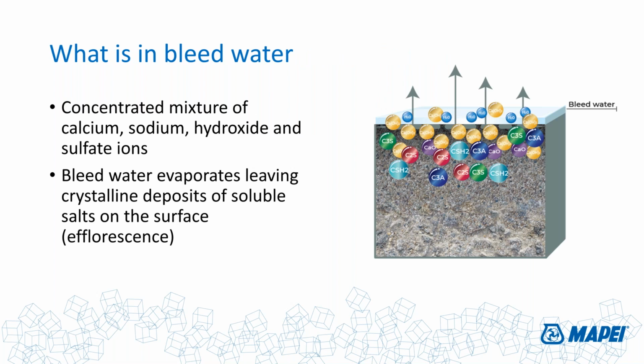That is again a concentrated mixture of calcium and sodium and hydroxide and sulfate ions that sit on the surface. And as that bleed water evaporates, if you don't work it back into the concrete over time, it's going to leave a salt deposit on the surface. Calcium hydroxide is going to get into its crystalline form. The sulfates will go into their crystalline form, all of which you might want to consider or call efflorescence. This is the white crystalline structure that you see on some concrete slabs. It's very brittle. You can take your razor and scrape off the surface of it. But this is what's coming out of the evaporation process of that bleed water that shows on the surface.